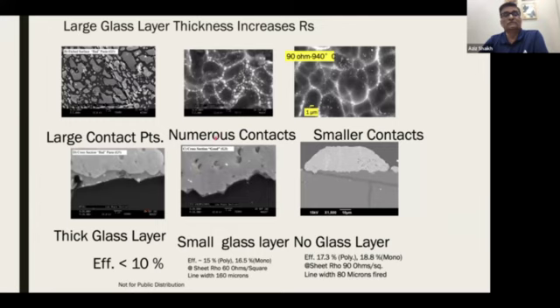So this shows you a little bit of flare. What you see here are the pictures where the top silver grid lines that you saw in the earlier picture were etched out. If you have a very bad cell, then the silver grid line and silicon wafer have a thick layer of glass, because to make the silver grid line stick to the silicon wafer, we have to add the glass. If you have such a situation, you get very low efficiency. A good situation is where you have a thin layer of glass. If you etch out the layer, now you don't see these big puddles of glass, but you see a bunch of white dots, which are actually silver dots, which form channels to carry the carriers from the silicon wafer to the grid line.